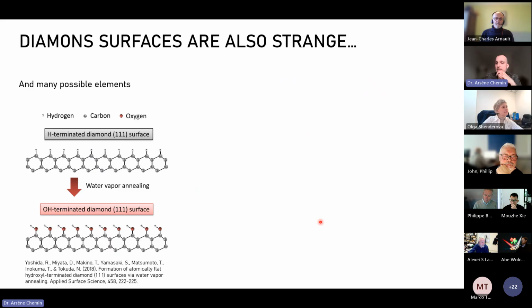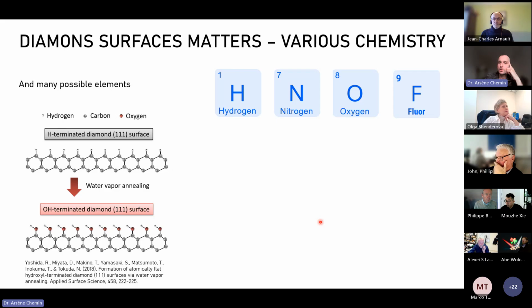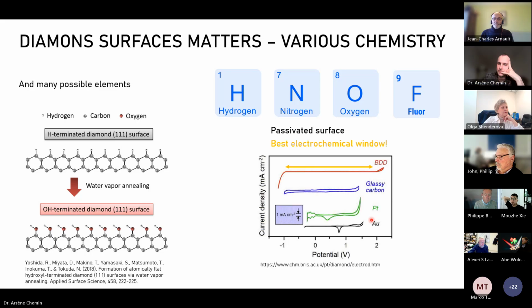And of course, you can terminate diamond with many different atoms. So I just talked about oxygen, but as you know, when you grow diamond by CVD, the main termination is actually hydrogen. So you will have clean hydrogen layers at the surface. But that's not even all. You can even have different kinds of atoms, such as nitrogen or fluorine, that have been more and more investigated in the late years to terminate diamonds.